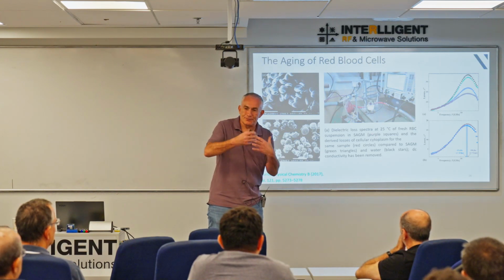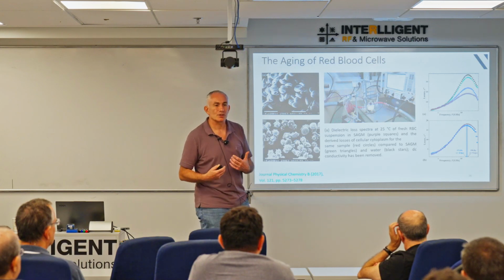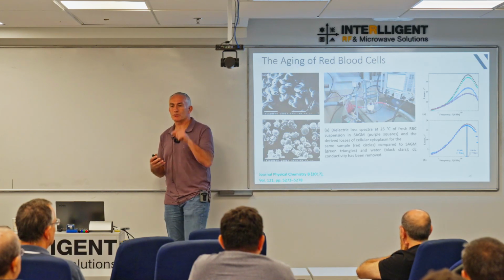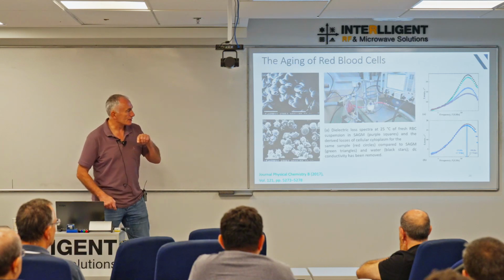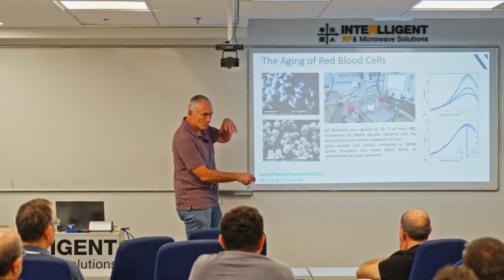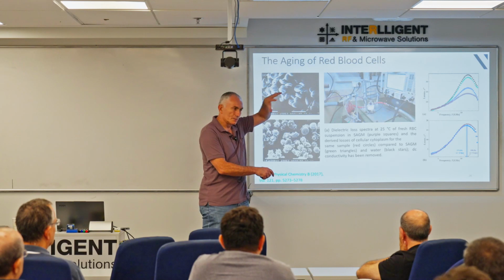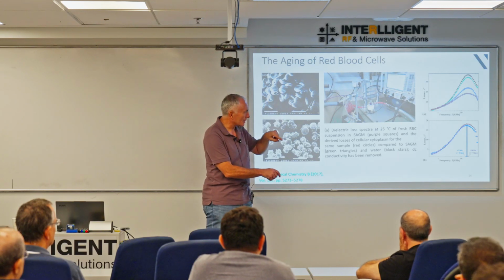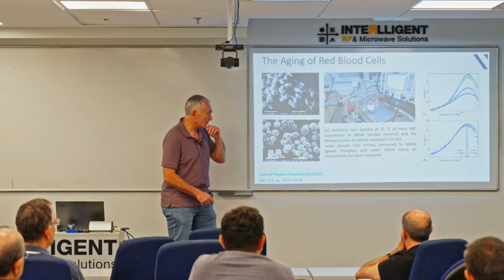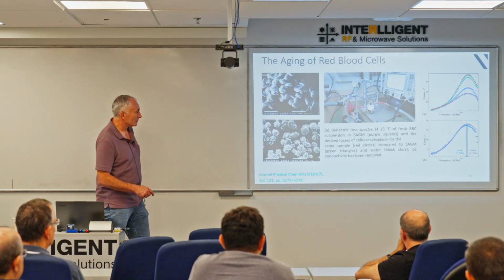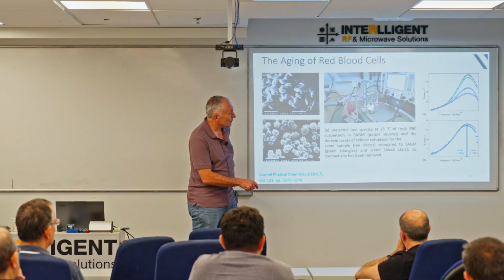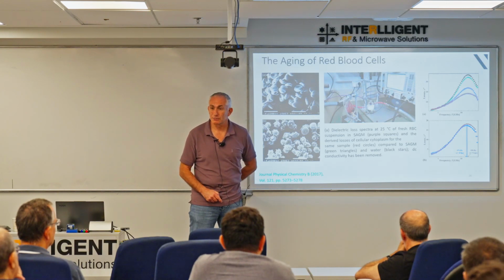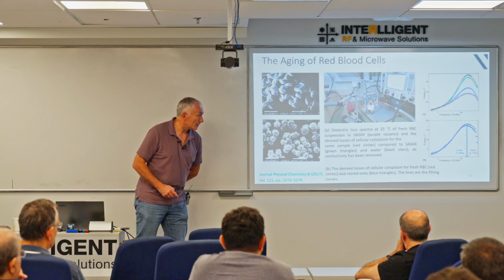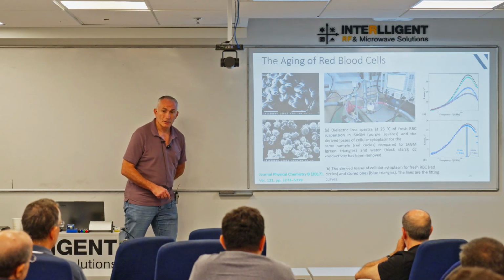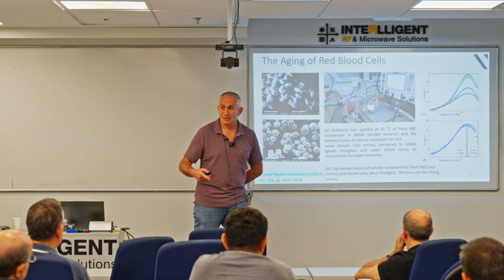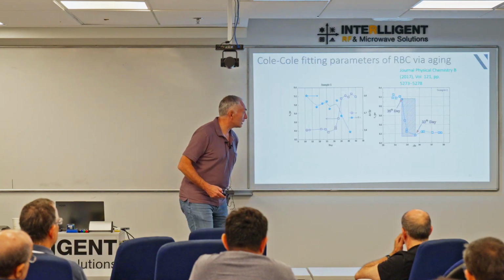And we have models which allow us to actually look at the cytoplasmic water, the water inside the blood cell itself. So that's the actual sample, and this is what we get when we remove the buffer solution and look at the water inside the sample itself. We can see this. Okay? Now, after a while, we see things begin to change in these signals. They change quite significantly. And in fact, when we do a fitting of those, and we start looking at different days that they've been in storage, you start to see this.